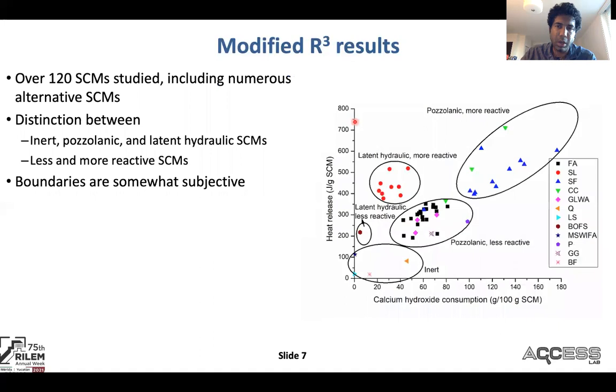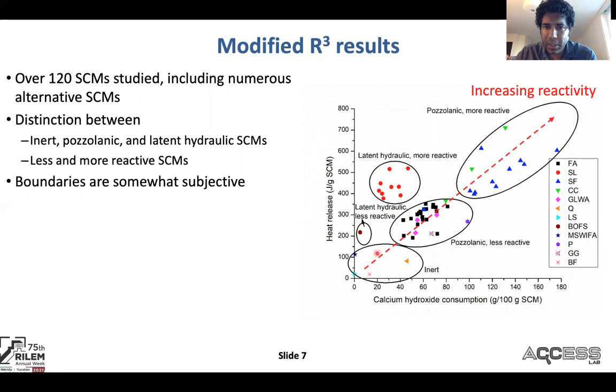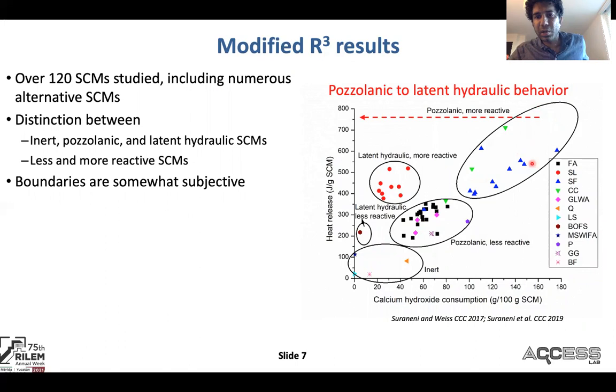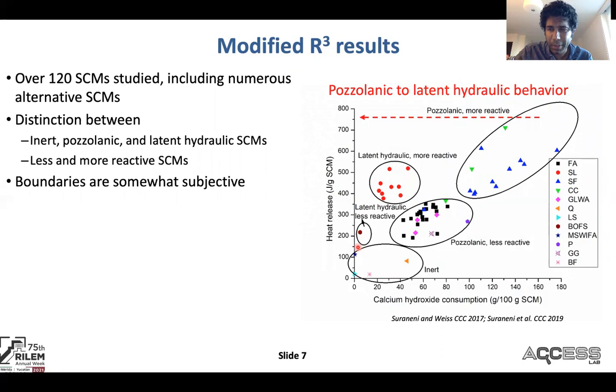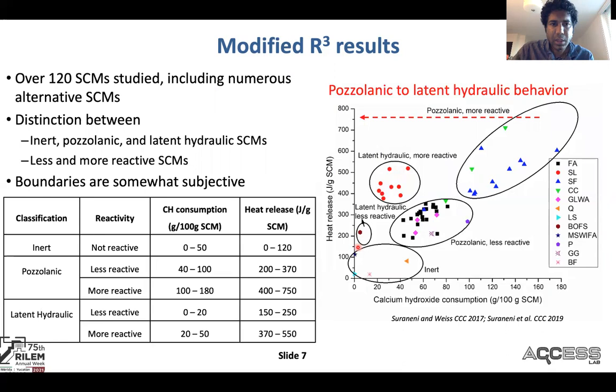We've tested now well over 120 different materials, including a lot of alternative and sometimes honestly strange SCMs, and we can distinguish inert, pozzolanic, and latent hydraulic SCMs. As reactivity increases, materials move along one axis, and going from pozzolanic to latent hydraulic is reflected in lower calcium hydroxide consumption at the same levels of heat release. The boundaries are subjective — reactivity is kind of continuous, so whatever boundaries you choose will have some level of subjectivity, but our current numbers seem to work reasonably well.